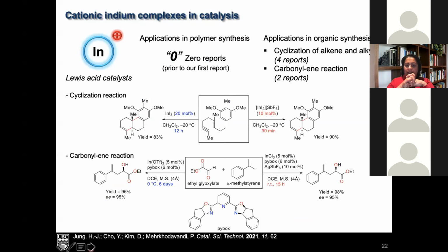But actually, if you look in the literature, and my student June did, during the pandemic lockdown last year, he actually wrote a review article on this in this issue, which was that there were 0 reports of cationic indium complexes in polymer synthesis. There just weren't any. And even in catalysis, there are exactly 6 reports in all of organic or inorganic catalysis for cationic indium complexes in catalysis. And it was surprising, because in 2 of these you see that cationic systems are actually more active than the neutral systems. So we were excited about this.